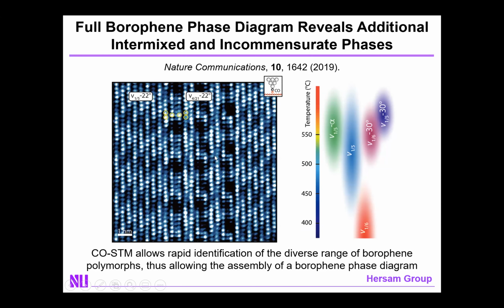And since those form more extended superlattice structures, it allows you to realize additional phases, in this case, the so-called V4/21 structure with a 22-degree rotation with respect to the silver lattice. The bottom line is that borophene is almost endlessly interesting in that it's highly polymorphic like the bulk, and as a result, it doesn't constitute one material, but rather a family of materials.